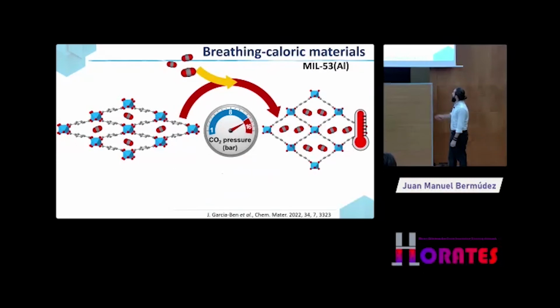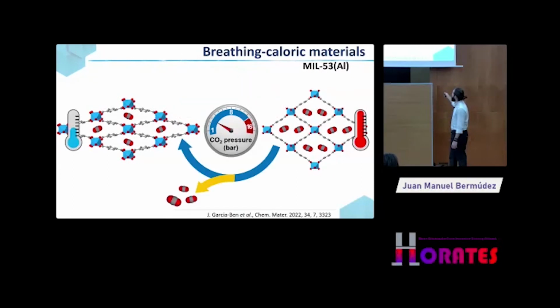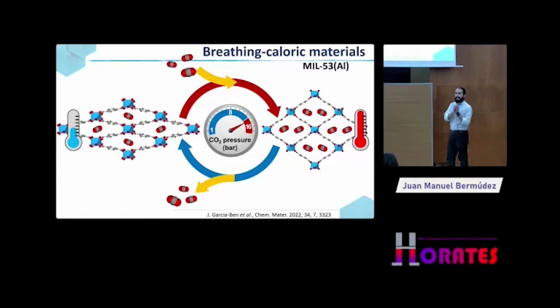And we observed that when you drive the transition upon pressurization, your materials heat up. It is an exothermic transition. And then when you release the pressurization, your material cools down, and now that it's cold, you can use it to absorb. It is really interesting that here you have two contributions to these thermal changes.